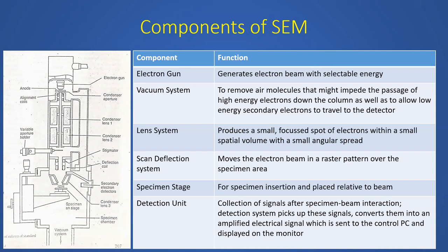In TEMs, you want the electrons to transmit through the specimen. You want very highly energetic electrons to be able to transmit through comparatively thick specimens. For a 120 kV, a 100 nanometer thick section would be okay, but for a 300 kV, maybe you can work with a 200 nanometer section. That's the purpose with TEMs. But for SEM, you're only concerned with the secondary electrons, which come from very close to the surface of the specimen. So you don't want highly energetic electrons that will penetrate through the specimen. That's why typically it's around 30 kV. So that's the electron gun.